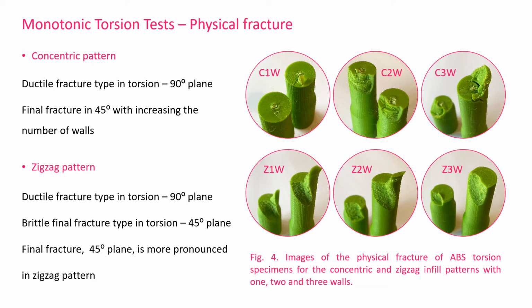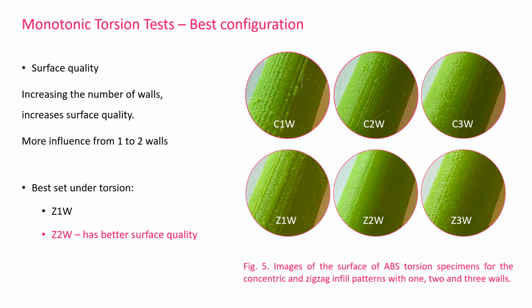The zigzag pattern also shows similar behavior, thus being characterized by crack initiation and propagation in a 90-degree plane, but in this case, there is a bigger influence of the infill pattern, resulting in more pronounced fracture surfaces in the 45-degree plane. In both patterns, an increase of contours from 1 to 2 walls proved to be beneficial for the improvement of surface quality of the specimens, with no relevant difference between 2 and 3 walls, as can be seen in Figure 5.